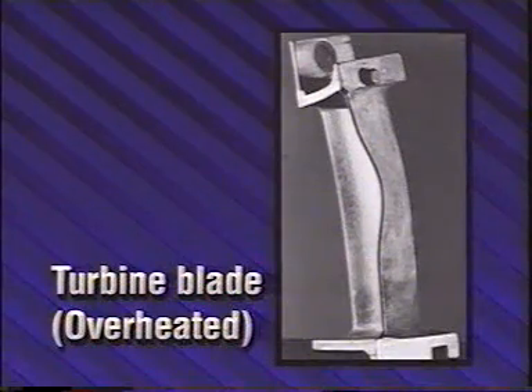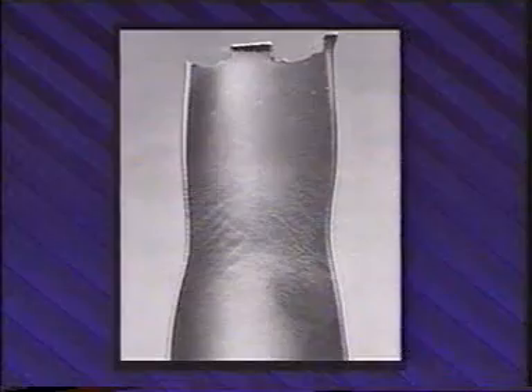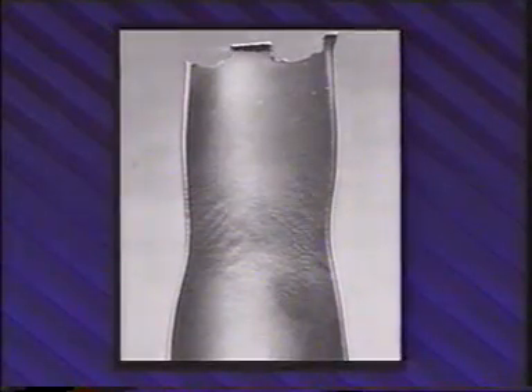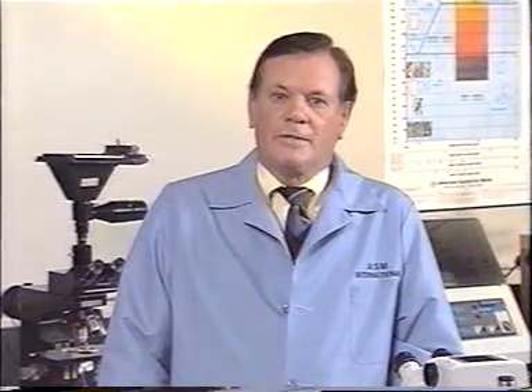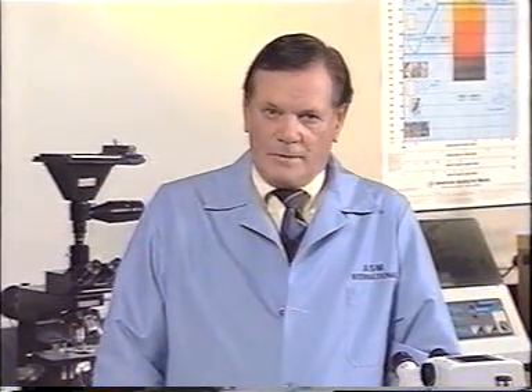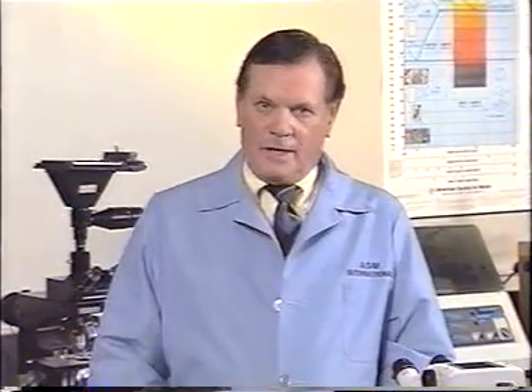Rotating components can stretch, often beyond limits, causing them to make contact with nearby stationary components. The result is rubbing deformation and failure. Fatigue is a fairly common cause of cracking in turbine blades and vanes. Fractures originate from the highest stress locations or from critically located defects. Fatigue fracture can also originate at notches caused by FOD, which is short for foreign object damage.